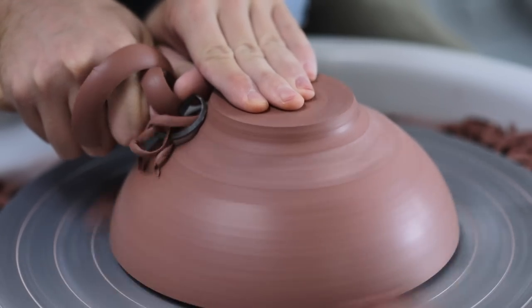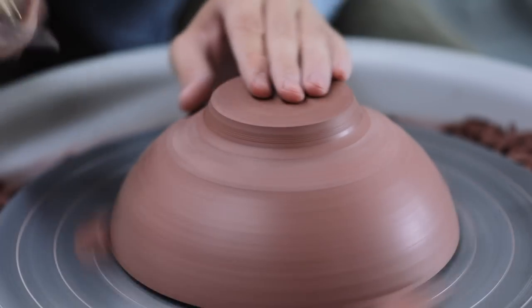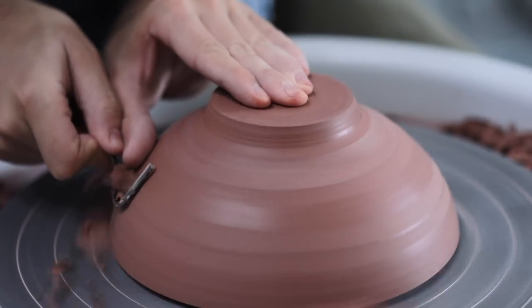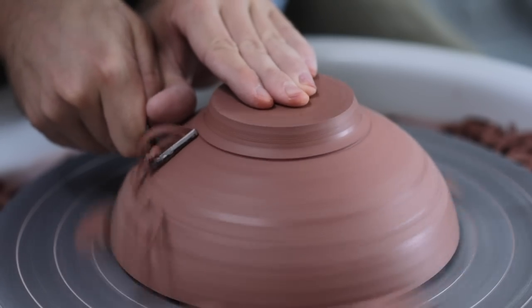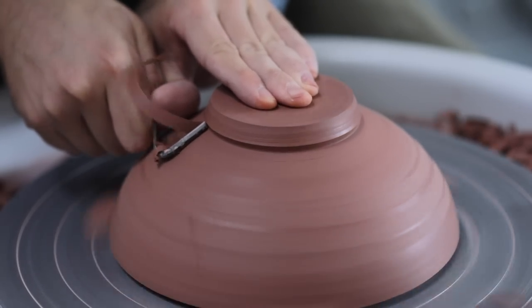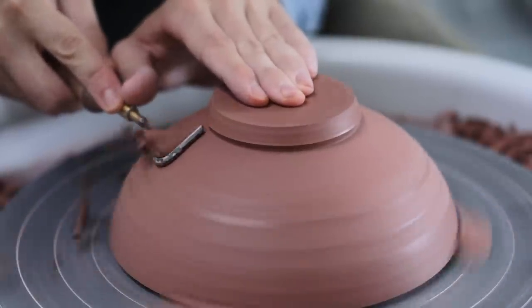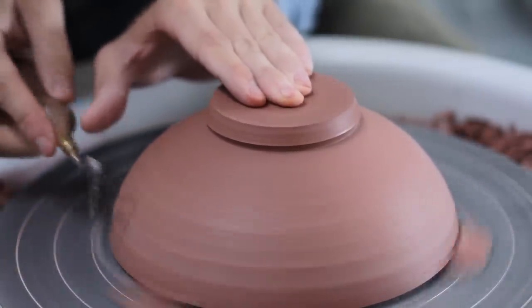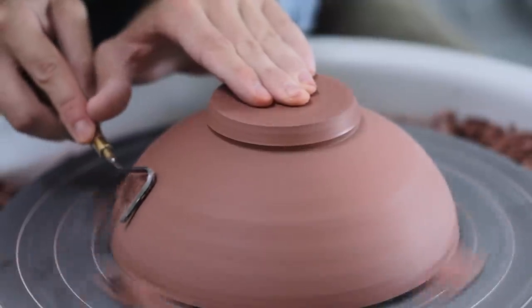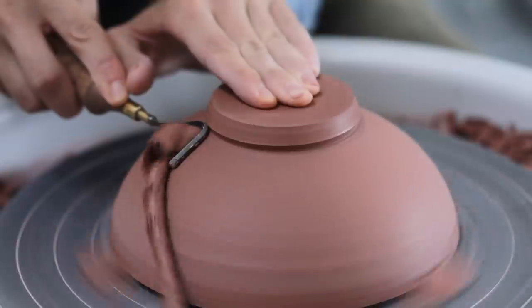I can now use my sharp tungsten carbide turning tools to really refine the underside of the pot, the foot ring especially. You can see that the clay is a little bit on the dry side, as when the clay is shaved away it sometimes comes off in small fragments. And it's entirely my fault, I shouldn't leave pots out, exposed to the open air when I leave my electric kiln firing overnight. You can see it's worse towards the rim, and then as I work my way up the form, the stoneware gets gradually damper and the clay comes off in nicer ribbons.